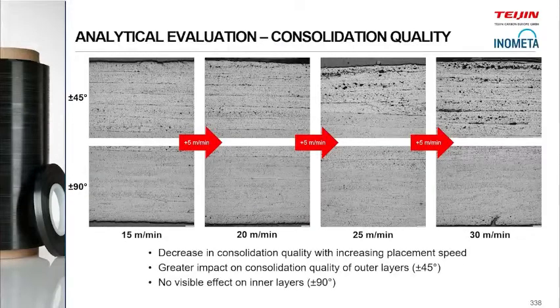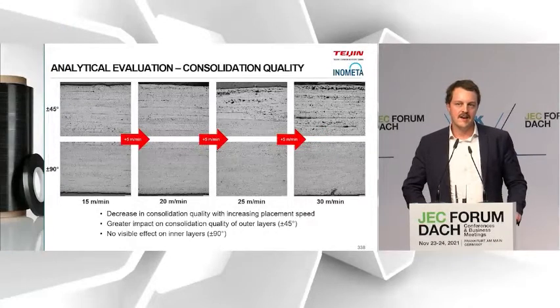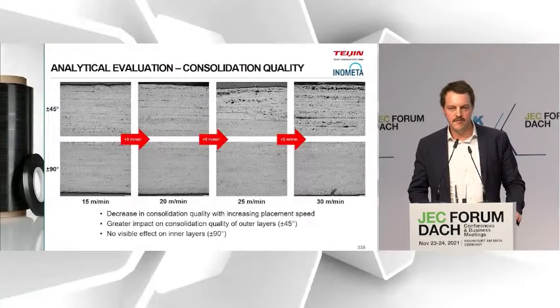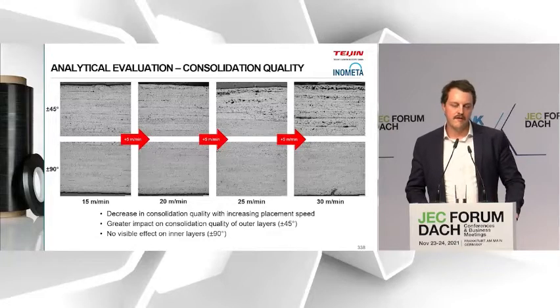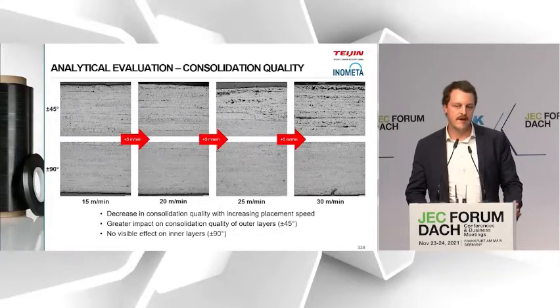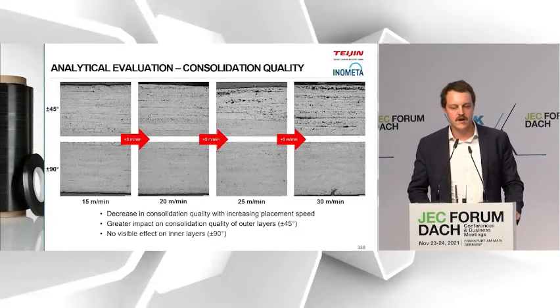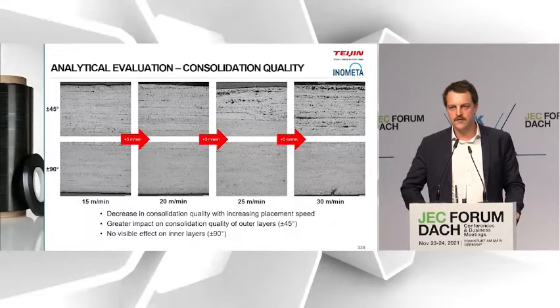But on the more inner layers, you do not see that effect as drastically as you see on the top layers. It's basically due to the fact that the material sees, with every layer we put on, a completely different thermal history than the outer layers. And therefore we need to find a process window where we can achieve the best consolidation quality for each type of material. So we started that iterative process to quickly evaluate and take the measures and changes on the trials that we are running.